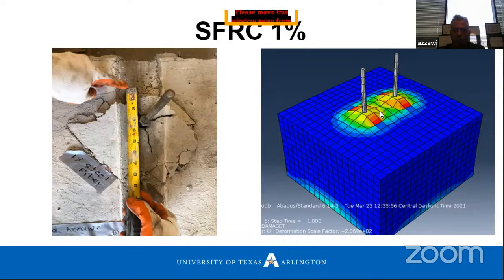We measured how much. This is for 0.5% steel fiber ratio. So the concrete breakout failure is a little bit less compared with 0%, and with 1%, as you see, the damage is less compared with 0%. The damage is less.